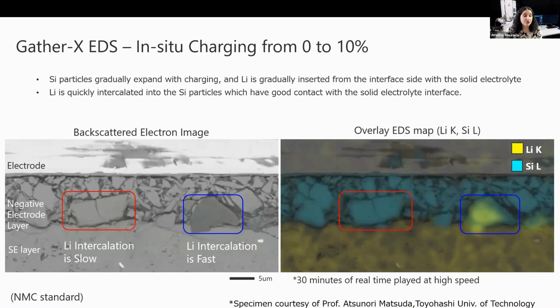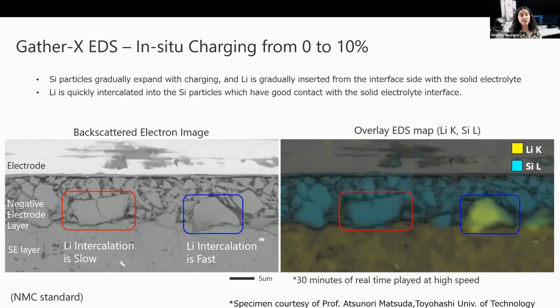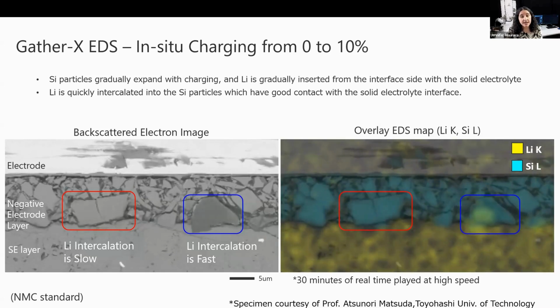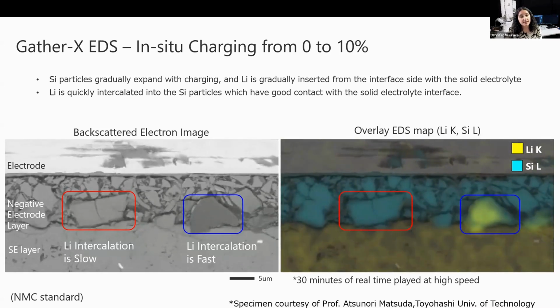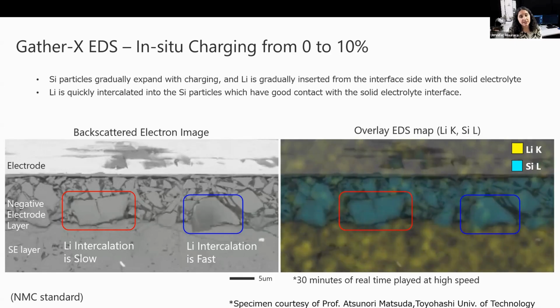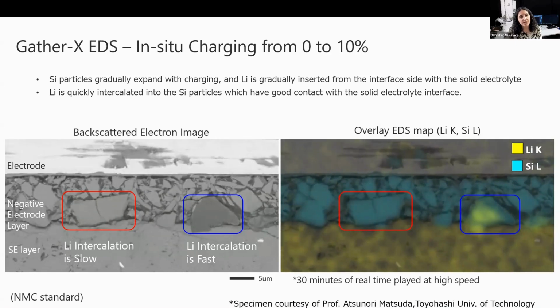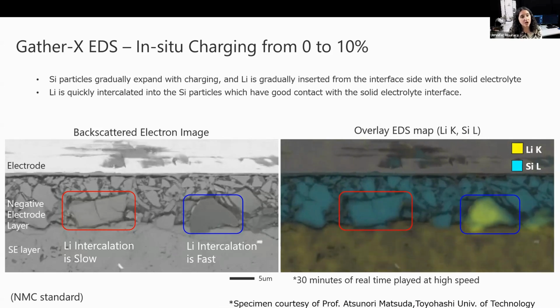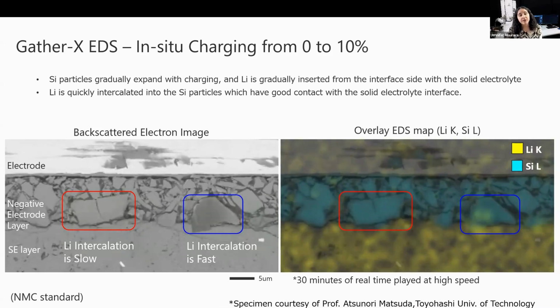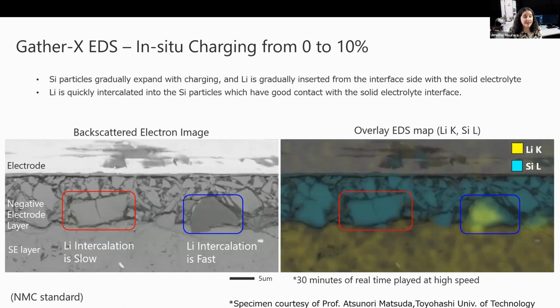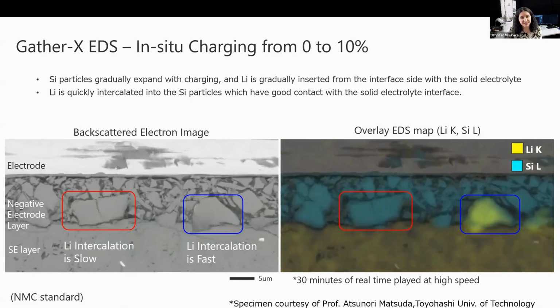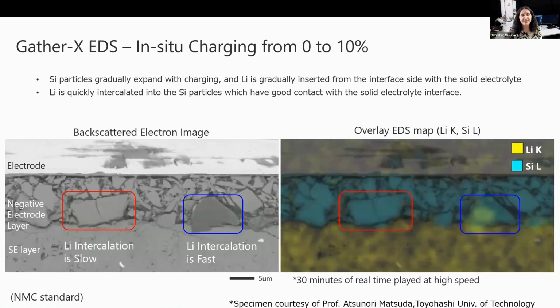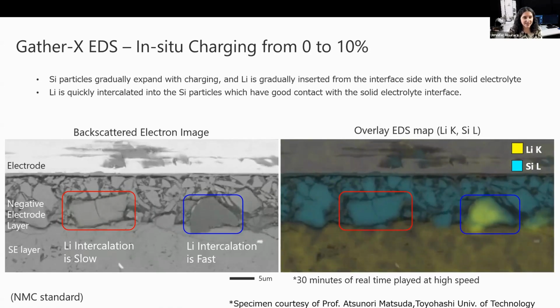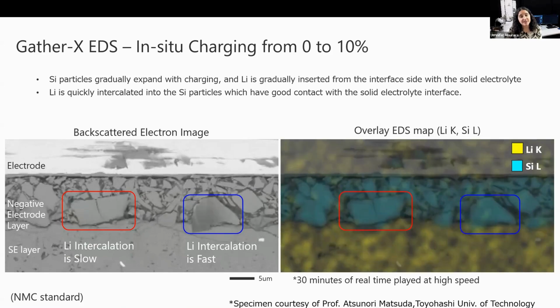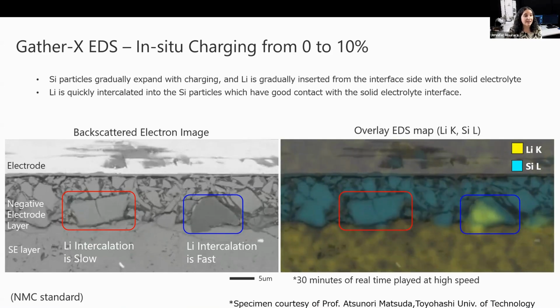In addition to the gradual expansion of silicon particles as a result of charging, from the EDS maps, we were able to observe how lithium gradually intercalated into a silicon particle at the interface between the silicon negative electrode and the solid electrolyte. Furthermore, from the fact that lithium was selectively inserted into some of the silicon particles that are in contact with the interface, it was revealed that there are certain silicon particles that are more easily alloyed with lithium.